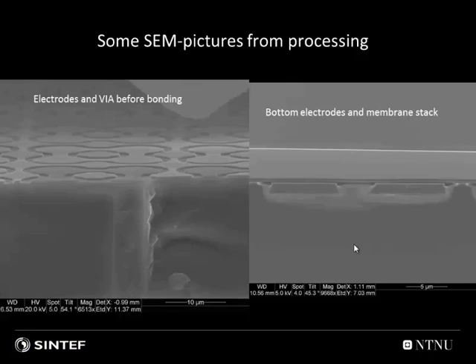So, two SEM pictures from the processing. This is the wafer at the stage before bonding. You can see the 2x2 elements. You can imagine that this is a bit lower than here. It's not easy. It's a 60 nanometer height difference, and I think it's only the isolating oxide. I don't think we reached the middle of this, which is the via. It's polysilicon filled. And you can see here, not very sharp, how this is the isolating oxide, and you have crystalline silicon for the bond interface. This is the membrane stack after wafer bonding. You can see the gap, the polysilicon electrodes, and isolating oxide.